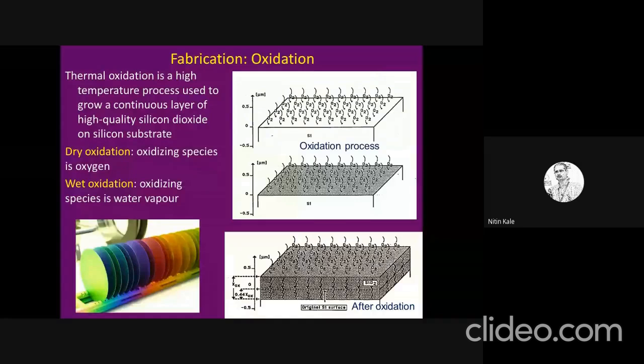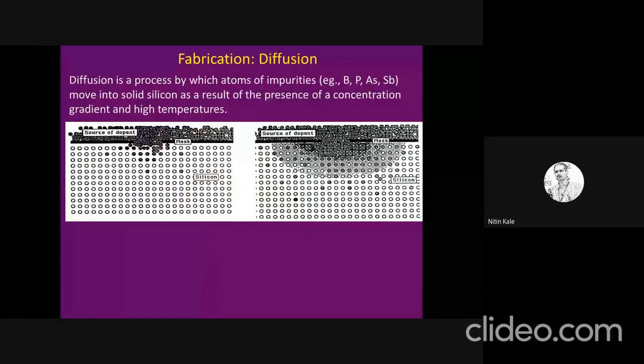Okay, one important thing is, as you increase the temperature, the oxygen molecules tend to go deeper and deeper inside the silicon wafer. So that's a growth process. Silicon is getting converted into silicon dioxide. That is important here: there is a chemical reaction between the silicon and oxygen. And the higher the temperature, the deeper the oxide can grow into the silicon. What is important is that silicon is getting consumed in the process of oxidation. So that is why it is called a growth process. And this is different from deposition. I'll come to deposition very soon.